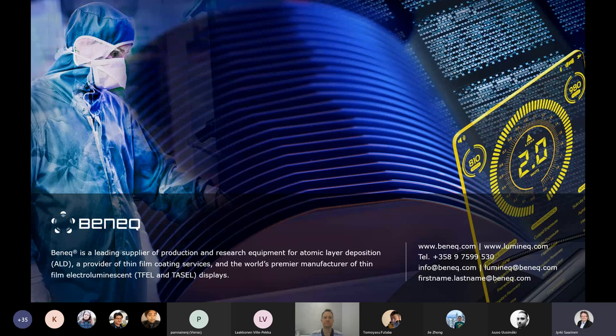Right. Does the conformal nature of ALD help to reduce the surface roughness of materials with titanium oxide coating? Yes, it is true that ALD can be used to reduce the surface roughness. ALD coating can very nicely smoothen out any holes or cracks, these kinds of valleys. But when you have peaks, some spikes on the surface, those will not be removed. They will just be coated conformally. So it will efficiently remove all the valleys, but only make the peaks a little bit broader.